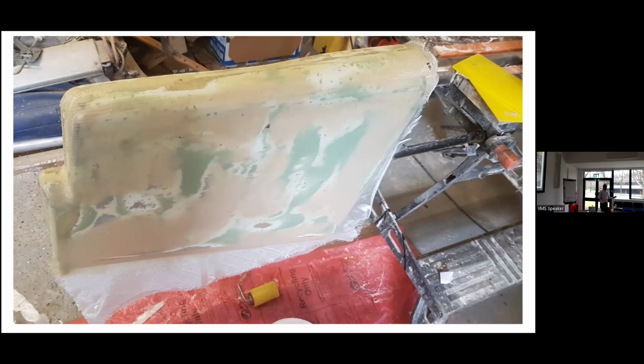If you're ever asked about that by a boatyard, what would you suggest as a format for this repair? I would recommend multiple layers of 450 gram biaxial fabric. Generally, it's 300, 450, or 600 gram. 600 grams is a bit unwieldy for an operative to work with. 300 grams is just too light to stay there. It doesn't hold enough resin to stay down. 450 is like an optimum weight. So that would be our recommendation.